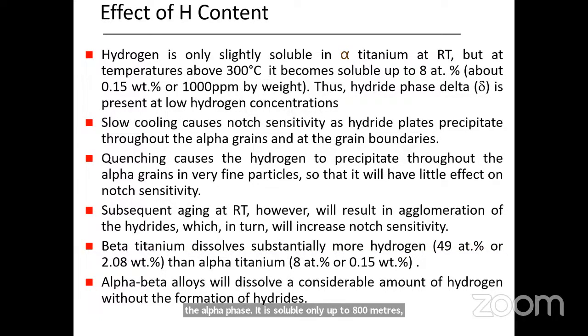If the alloy is slowly cooled from the alpha phase field, the hydride starts precipitating out. Even if you cool slowly, it causes a notch sensitivity because hydride starts precipitating out throughout the alpha grains and also at the grain boundaries. When you quench it from the alpha phase field, hydrogen precipitates throughout the alpha grains in very fine particles, but it will have little effect on notch sensitivity. But when you start aging, again this agglomeration of hydrides will take place, and again it will increase the notch